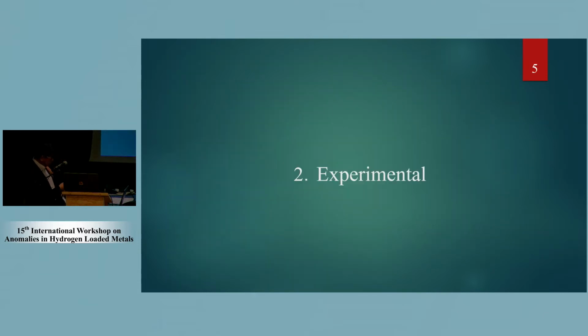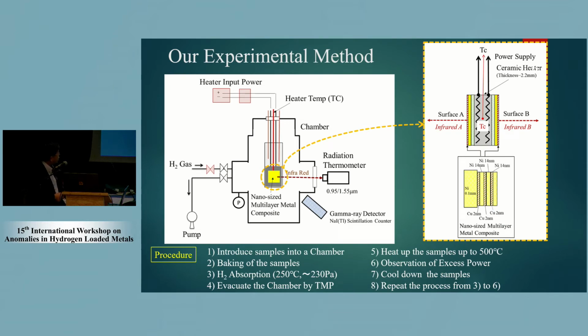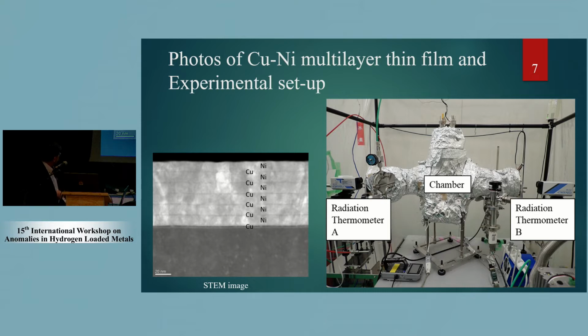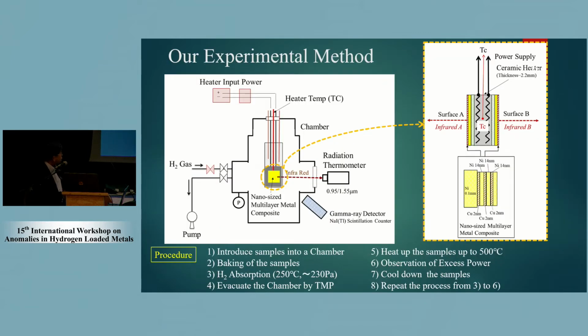Okay, I would like to explain our method. We use nano-sized multilayer metal composite like this one. Before the experiment, this is a nickel bulk with copper and nickel layers. The standard sample has copper at 2 nanometers and nickel at 14 nanometers. We prepared two samples, and they are heated by a ceramic heater. Temperature measurement and heat estimation are by the thermocouple embedded in the ceramic heater, and we also check the surface temperature by infrared, surface A and surface B.